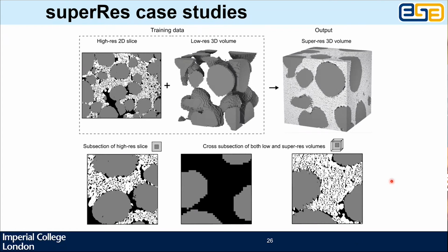So those three, we all started with the high-res 3D 3-phase. But with this one, it's just two data sets from NREL. One is an SEM image of the carbon binder domain, pore, and active material. Another is an XCT image of just the active material where the CBD is invisible. And then we've super resolved it. And you end up seeing some really interesting large features as well as these very tiny features in the way that the CBD ends up being distributed next to the active materials, which reflects what's observed in the high resolution SEM data.